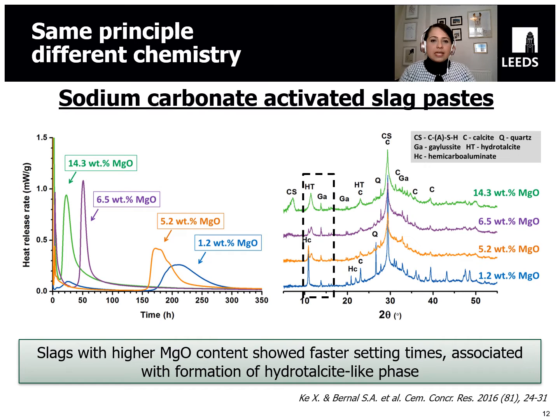So what was really interesting is we identified that as the magnesium oxide content increased in the slag, we favored the formation of these layered double hydroxide hydrotalcites. And it seems like the in situ formation of these phases somehow enables the consumption of the CO2 that will be present in the pore solution of these systems, and therefore that will speed up the process of reaction of these materials, because the pore solution will be very similar to what we can expect in a sodium hydroxide activated slag cement.